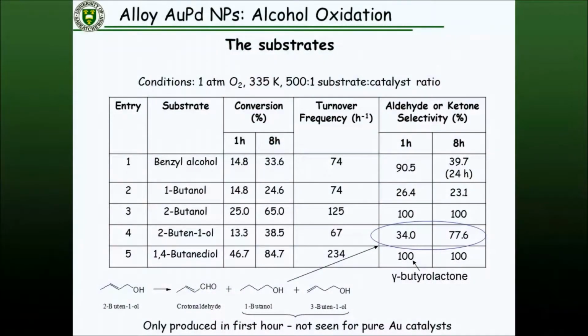One reaction kept standing out, and that was the allylic alcohols. There we started out with very poor selectivity towards the aldehyde, in this case the crotonaldehyde from the 2-buten-1-ol. But then over time it got more and more selective to that aldehyde. This is very unusual in a catalytic system, that your selectivity gets better and better as you go on. It seems to suggest that something was changing in our catalyst as the reaction was proceeding. So we continued to investigate this system and try to understand how these allylic alcohols react with palladium-gold particles such that we get better selectivities over time.